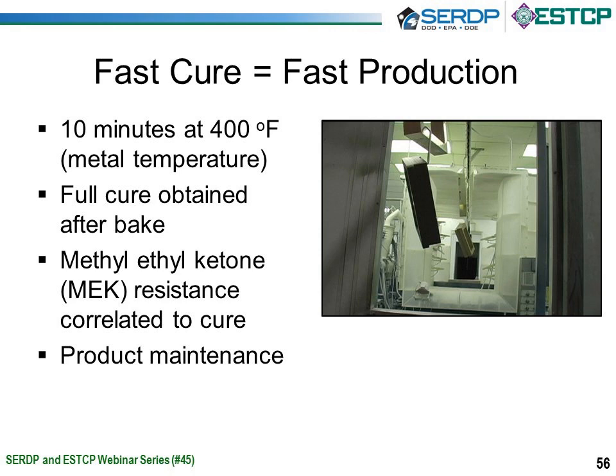The technology that was developed through this program requires a 10-minute bake at 400 degrees max. So that's metal temperature. It's important to note that that is not 10 minutes sitting in an oven that's set at 400 degrees. That's 10 minutes at the metal temperature that the coating is applied to. We need that 400 degree period to ensure that we get the proper cross-linking for the full cure.